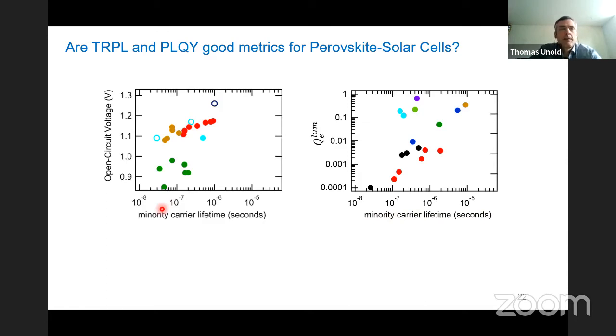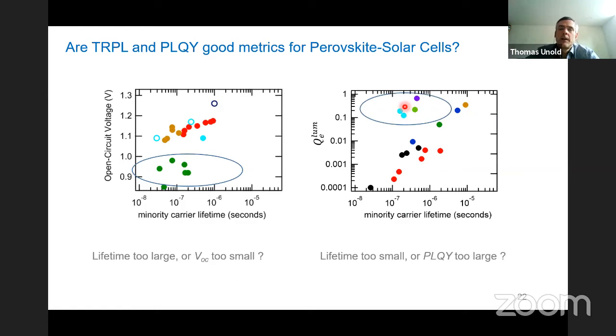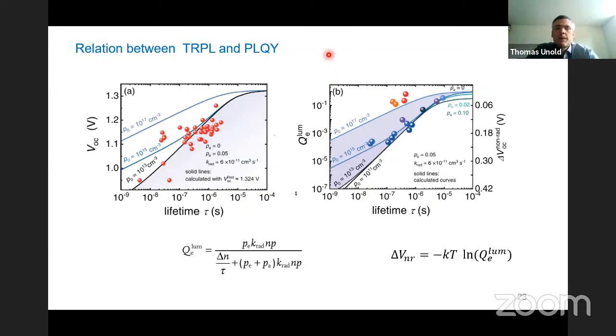What we did here, we took a lot of data from literature and looked at whether we could make sense out of it. And you can see, it scatters. There's some sense to it, but there are also some problems. There are some values that are very low, so the question is: is the lifetime here too large or the VOC too small? Here, there were some very high quantum efficiency values in the literature, 60% or something like that. So huge, and not very large lifetimes, actually. So the question is, was the lifetime measured too small, or was the PLQY too large? We discussed that a lot too. That was one motivation for this tutorial that we wrote. Of course there is at least an analytical relationship between the VOC and the lifetime, and also between the PL quantum efficiency and the lifetime, that's shown here.